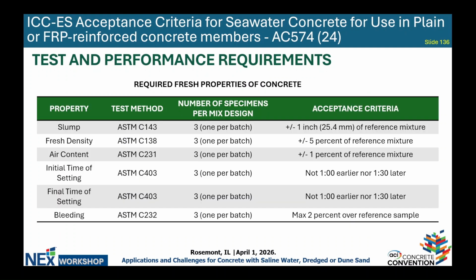So next up is our fresh properties. So we're requiring slump, fresh density, air content, initial and final time of setting, as well as bleeding. The number of specimens per mixed design should be 3, 1 per batch. And these are our acceptance criteria.